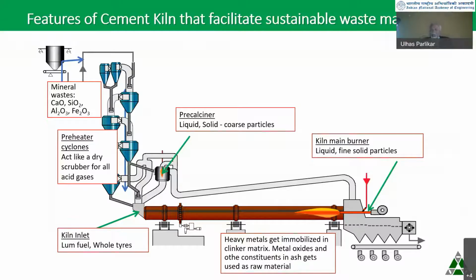So in this cement kiln, you have the option of feeding these waste materials as resources at 3 distinct locations. The first one is called the pre-calciner, which you see on top there. In this pre-calciner, we can feed liquids, we can feed solids which are coarse particles, and if you have gas also, you can feed them. The one on the left bottom corner, which is called the kiln inlet, there you can feed lump fuels.